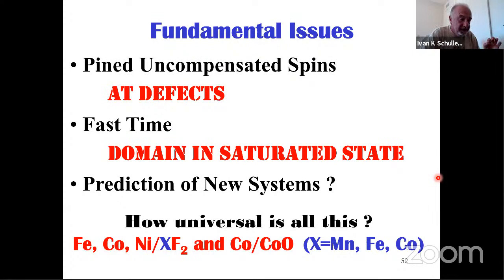And that's a very good controllable experiment: you can irradiate the materials with ions. When you irradiate the material with ions, you can produce defects in a controllable fashion, and not only that, you can produce them at different depths. This has very important consequences for the physics of many of these materials, not only exchange bias, but giant magnetoresistance, interfaces between ferromagnets, metal insulator transitions and so on. So yes, there is a way to control that, and that's a very interesting direction to go into. Thank you.